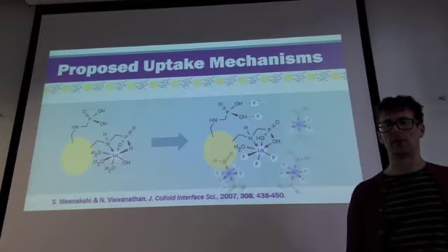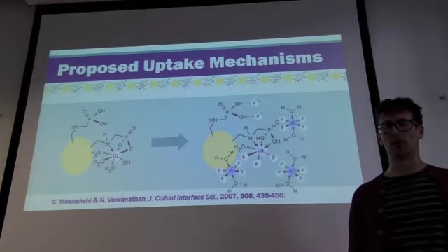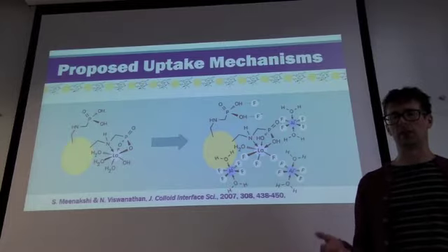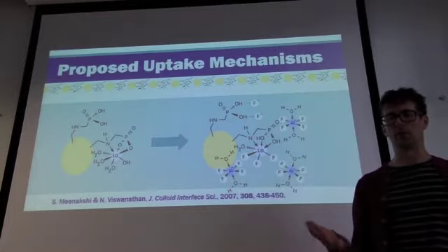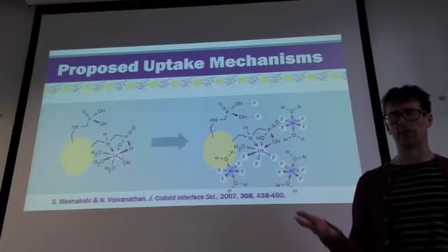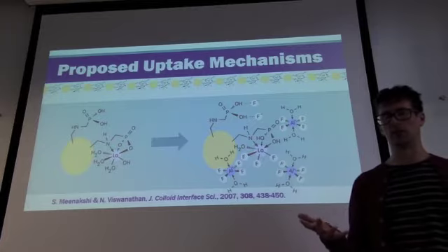What we then think happens is that a second, much slower uptake process takes over, dominated by the aqueous aluminium. We think it starts to form bridging complexes with the surface of the resin, and as it does so, it draws more fluoride out of solution with it.